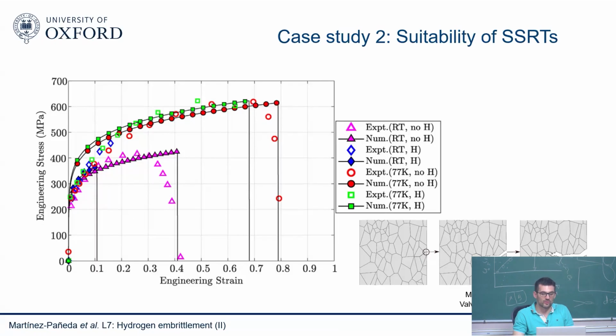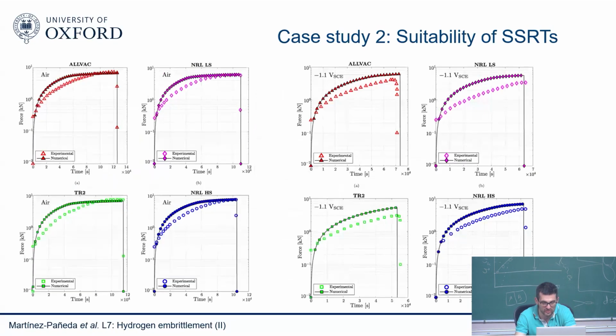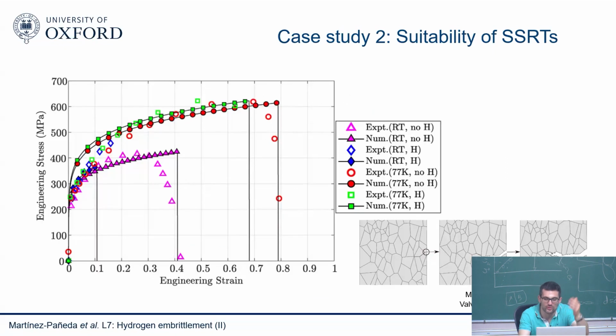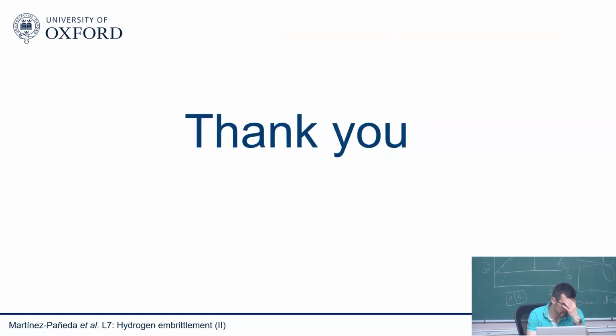We were capturing that in the absence of hydrogen, we predict ductile fracture as driven by the phase field. When we put the hydrogen in, even changing the temperature, because in this model you can change the temperature, I don't have the equations here, everything is Arrhenius laws, so you change the temperature, you change those binding energies, the diffusivity, and we can see that we also capture, qualitatively and quantitatively, from mechanism to time to failure and stress-strain curves, as you can see here. Okay, so that's all I had to say about hydrogen, or almost all. When we talk about multiphysics, I may have one result where we show you how to implement this in practice.